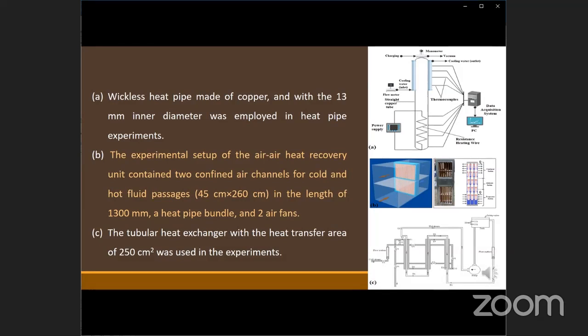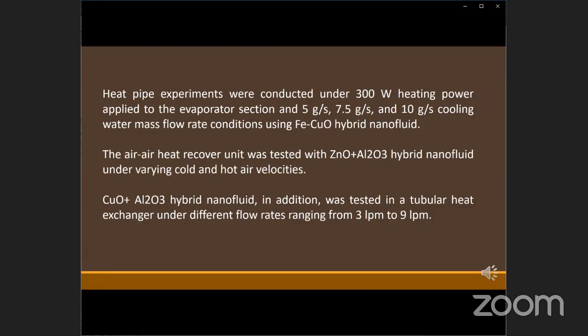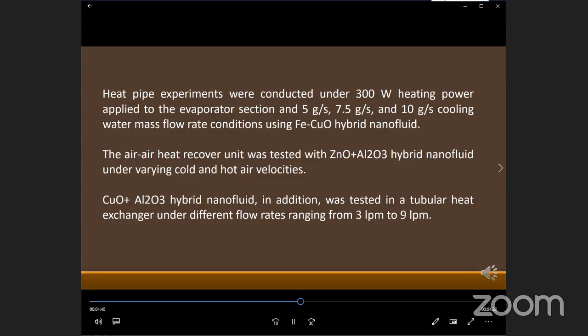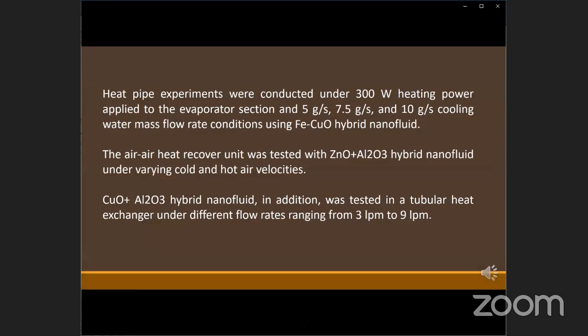in the experiments. Heat pipe experiments were conducted under 300 watt heating power applied to the evaporator section and 7.5 and 10 gram per second cooling water mass flow rate conditions using iron copper oxide hybrid nanofluid. The air-to-air heat recovery unit was tested with zinc oxide alumina hybrid nanofluid under varying cold and hot air velocities. And finally, copper oxide alumina hybrid nanofluid was tested in a tubular heat exchanger under different flow rates, varying from 3 to 9 LPM.